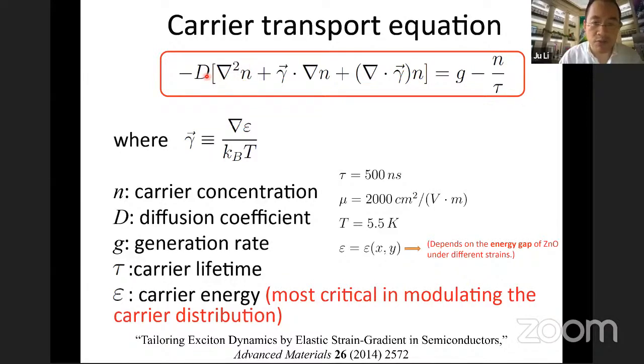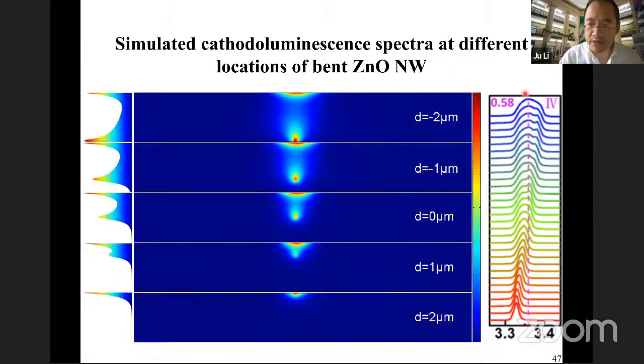So D is the random walk, the diffusivity. This is the drift term. So D over KBT is the mobility. This is the band gap gradient. But because the band gap depends on strain, this is also the strain gradient. And then this G is the delta function. That's the electron beam that we aim at the material that excites the electron hole pair. And then this N over tau is the photon that comes out with a single relaxation time approximation. So when we put in reasonable numbers for zinc oxide, we're able to fit the spectrum.